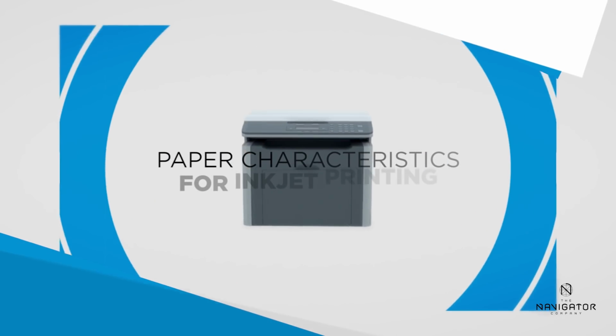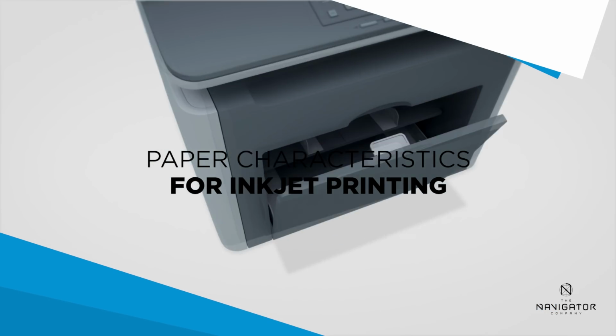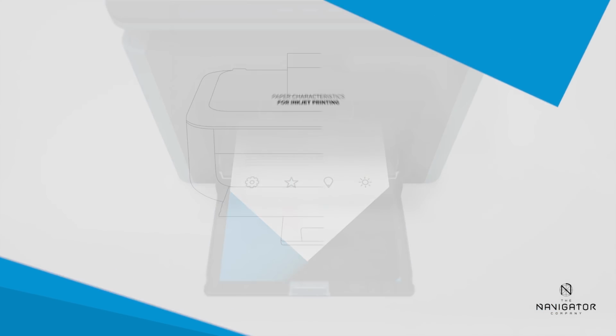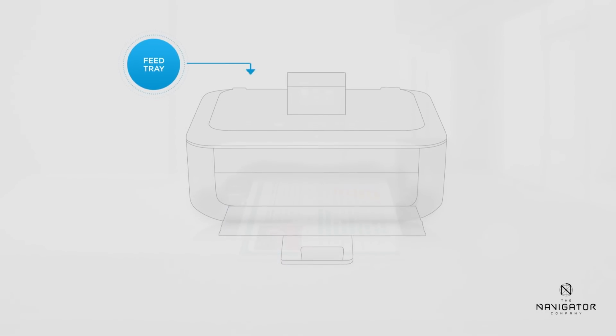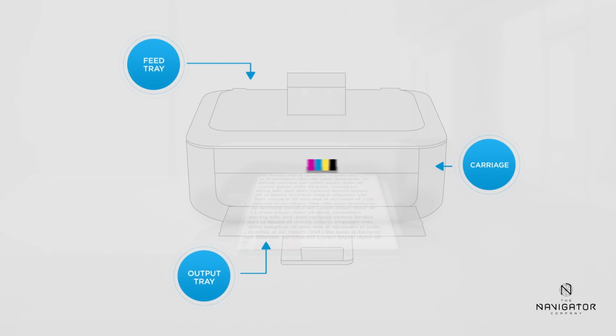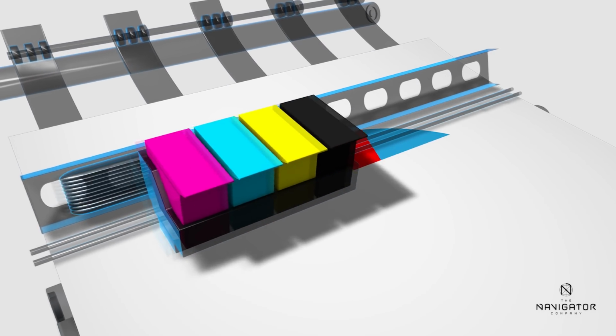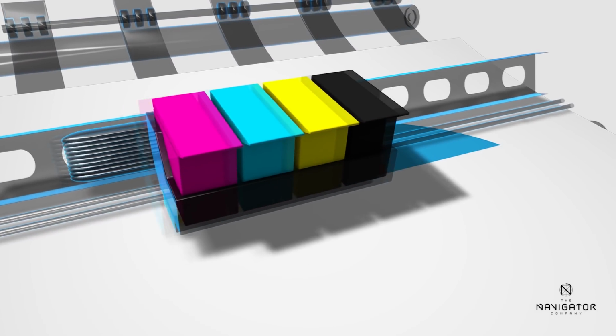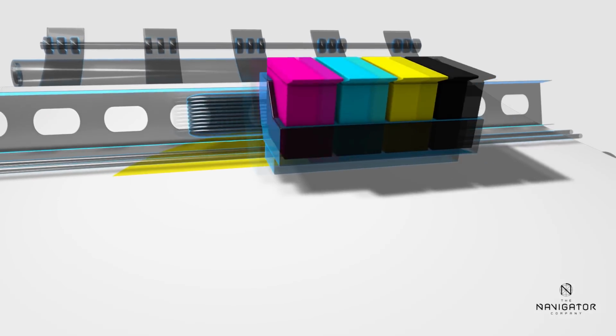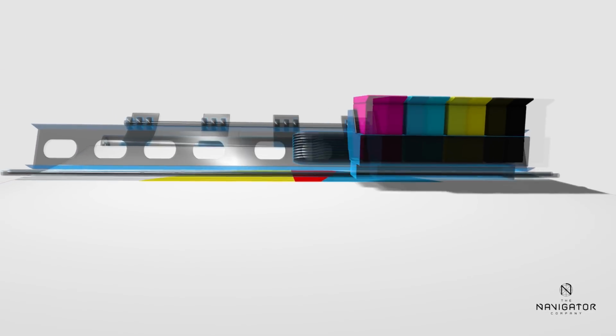For inkjet printing, there are also additional characteristics to keep in mind. Paper porosity is important while applying ink from an inkjet printer. The lower the paper porosity value, the less ink will soak into the sheet and the brighter the image. Too low a porosity can also result in the ink staying too much time on the paper surface, promoting color bleeding. The paper should have the right porosity to optimize both effects.